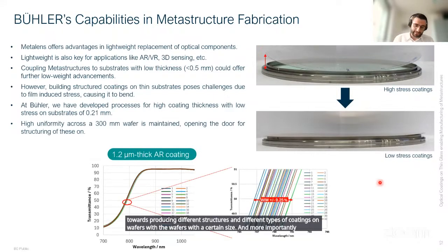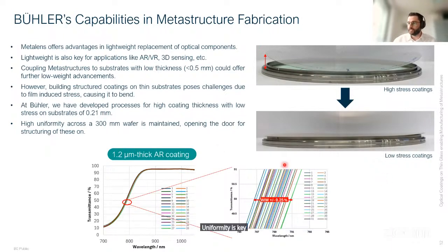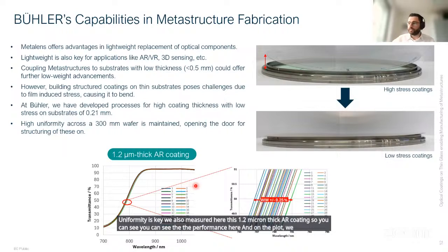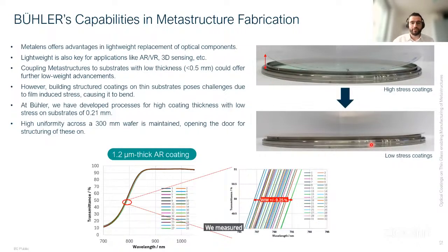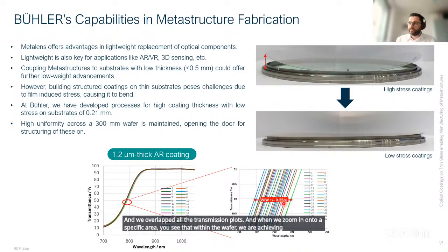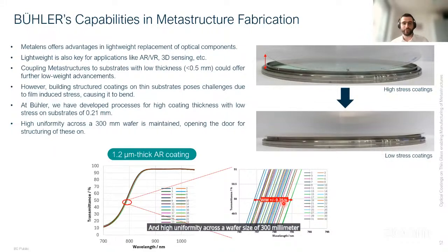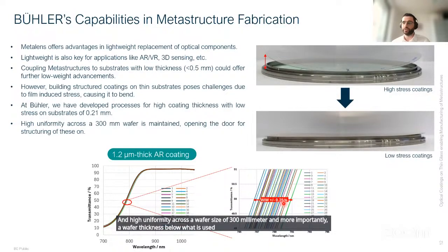And more importantly, because like I said before, uniformity is key. We also measured here this 1.2 micron thick AR coating. So you can see the performance here. And on the plot, we measured different points of the wafer that you are seeing here. We measured the performance on the different points across the wafer to understand if there is a variation of the optical performance. And we overlapped all the transmission plots. And when we zoom in onto a specific area, you see that within the wafer we are achieving plus minus 0.25%. So meaning we can actually do these thick coatings with low stress and high uniformity across a wafer size of 300 millimeter, and more importantly, a wafer thickness below what is used currently in the industry. And we have now solutions towards doing coating on thin glass, which we hope can benefit the field of metastructures.